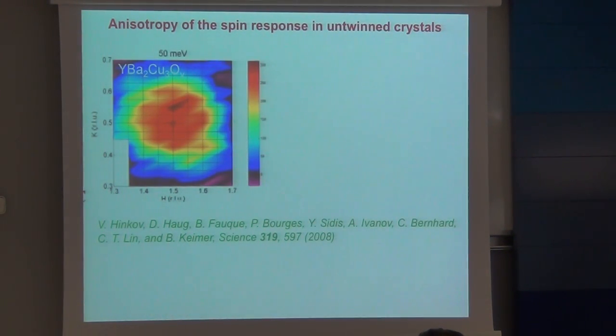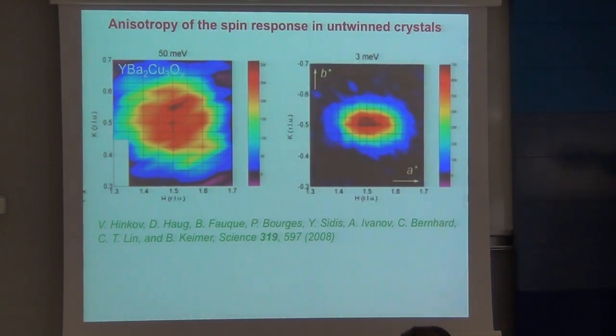The whole thing was given a lot of impetus by a neutron scattering experiment done by Bernhard Keimer's group, where they began down at the doping where Ando had seen the transport anisotropy. And if they went up to a high energy and did an inelastic neutron scattering measurement and tried to look at the line shape in X and Y and Kx and Ky space, they saw something pretty much isotropic. That wasn't a surprise. But when they went down to lower energies, they discovered that isotropic line shape systematically distorted to become strongly elliptical.